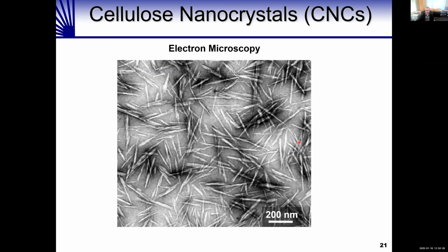So this is that electron microscope image of the cellulose nanocrystals. These cellulose nanocrystals are about 5 or 10 nanometers in diameter and maybe around 200 nanometers long. We have to use an electron microscope to image them because they are smaller than the wavelength of visible light—you can't see them with a regular microscope. Just to give you some context, you would have to put about 1,000 of these end to end to be the width of a single hair. So these are true nanomaterials.